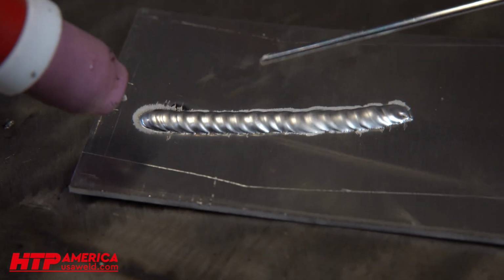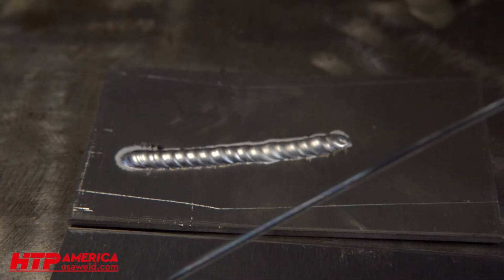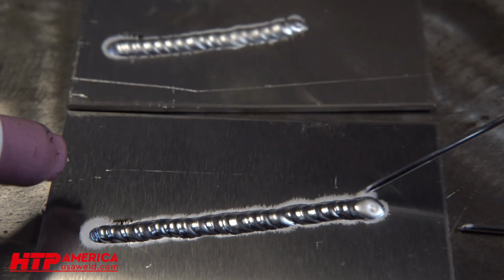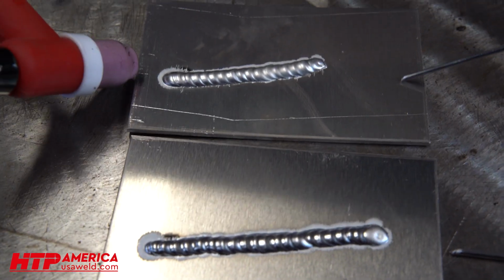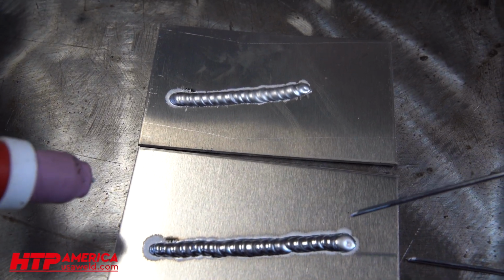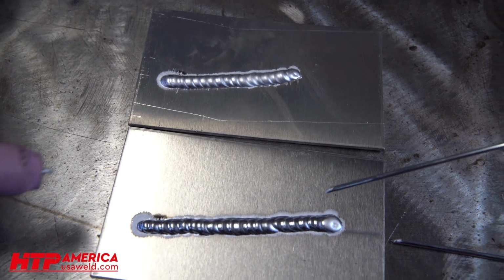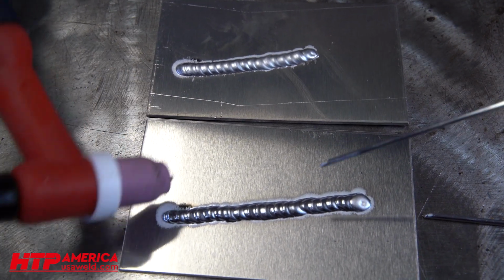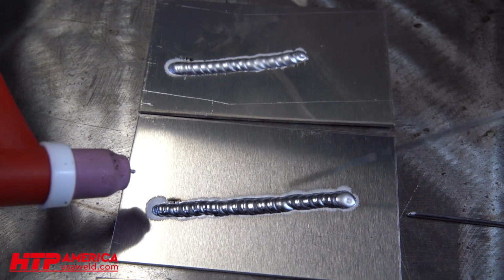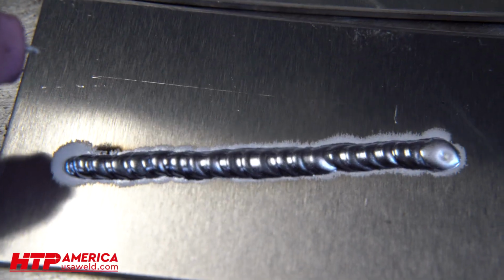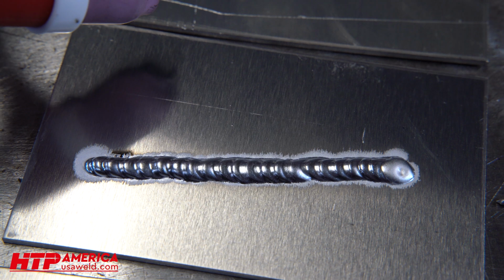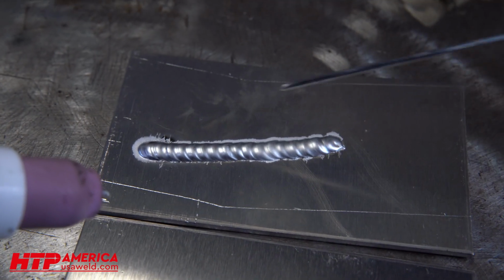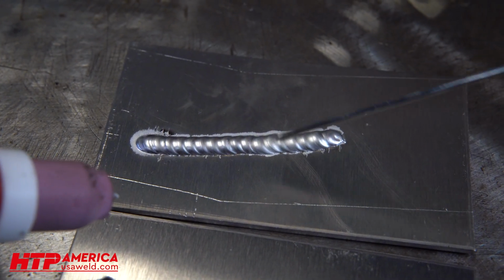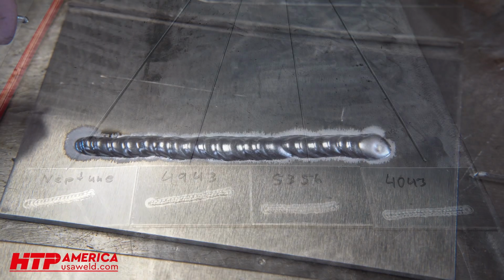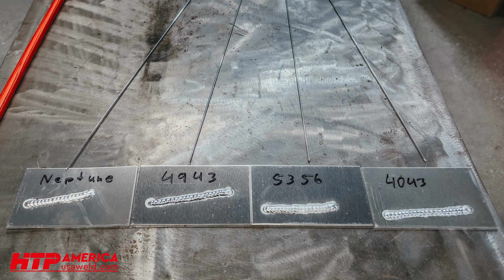And compare this to the 4943. Compare the etching, the cleaning zone. No change in balance, no change in frequency, no change in gas flow or front end consumables, all identical. These were welded within 60 seconds of each other on the same table. These coupons came out of the same box, and the etching zone here is a lot less than it is on this guy. So what did we learn?